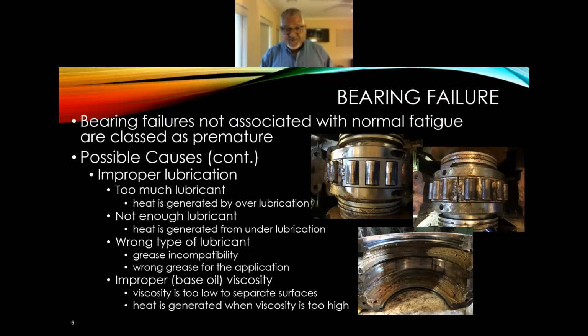Wrong type of lubricant could address grease incompatibility issues where you have a lithium complex grease in service and you want to move to a calcium sulfonate grease. They may or may not be compatible. Most obvious incompatibility is when you're mixing a clay-based grease with any other grease. When greases are incompatible, they'll usually soften and run out of the surface. Sometimes they'll harden and cake up in the bearing. Another example of wrong type of lubricant is just using the wrong type of grease for the application. And this is one reason why I'm speaking to operational savings by using calcium sulfonate greases.